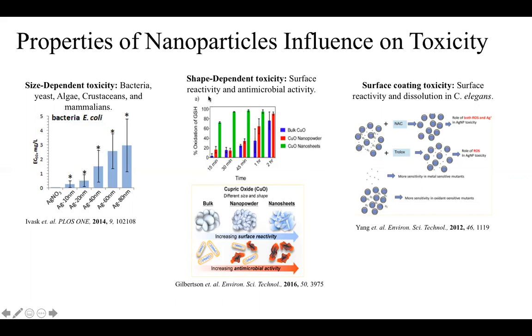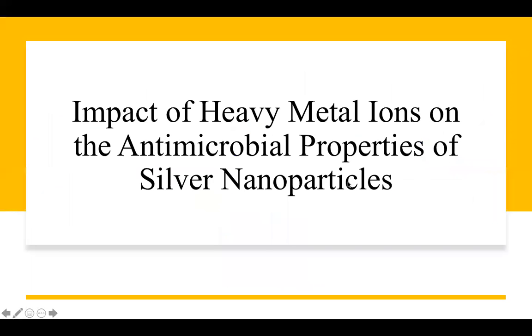So again, even though different pathways in different species, we're able to see how this is changing the pathways of growth that we're seeing. And even by different coating agents for looking at electrostatic versus polymer growth, using reactive oxygen species were grown in Yang's study to look at how toxic the uptake of nanoparticles is based on reactivity and dissolution within C. elegans. So it's really important to pay attention to all these different factors that change with our nanoparticle development. So this led to the meat of our study by looking at the impact of heavy metal ions on the antimicrobial properties of silver nanoparticles itself.